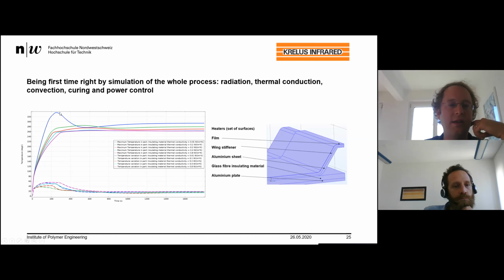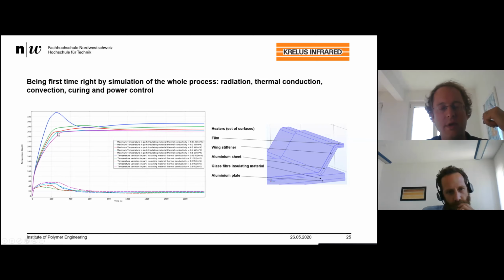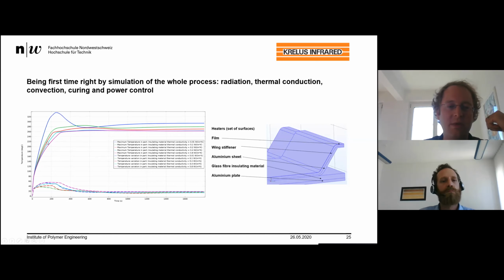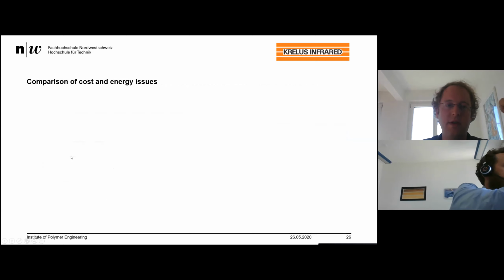And then we are getting a huge exothermal reaction, overheating of the part. The temperature is increasing up to 330 degrees, so not a really good process design. But if we tune this a little bit, we can create this heat flow through the thickness, and then together with the applied control of the system, we can reach a nicely smooth heat rate up to the shown 40 degrees per minute. So this was my part about the simulation.